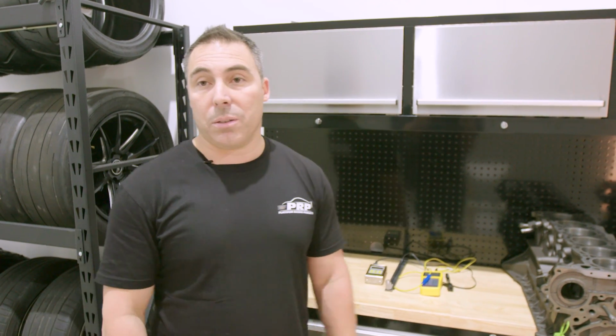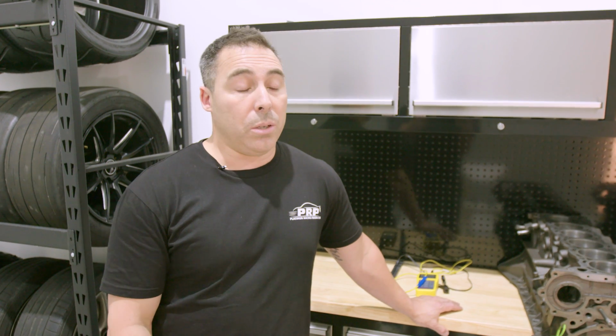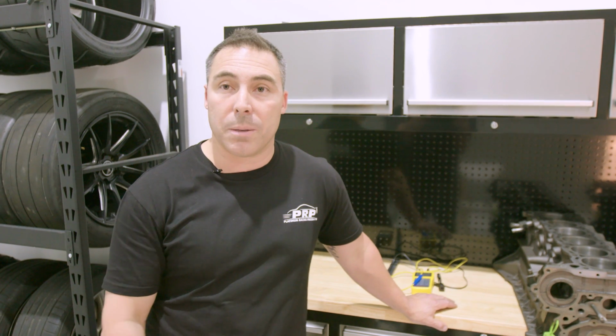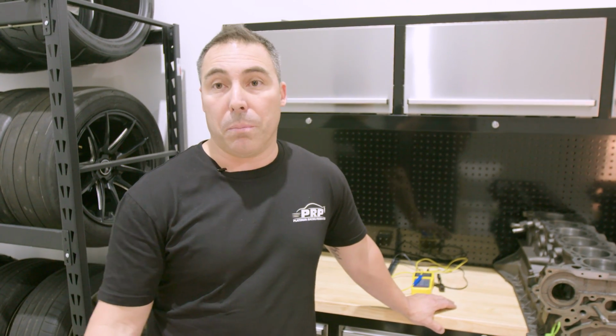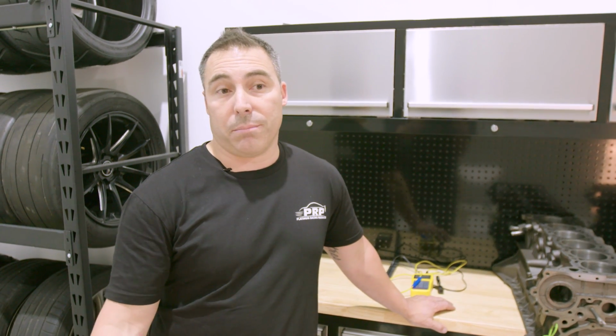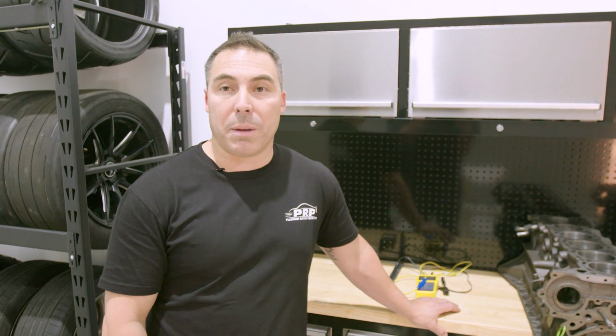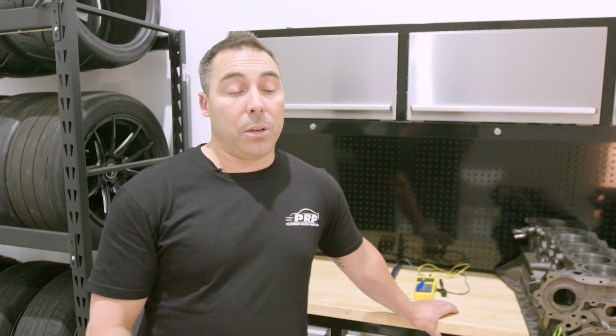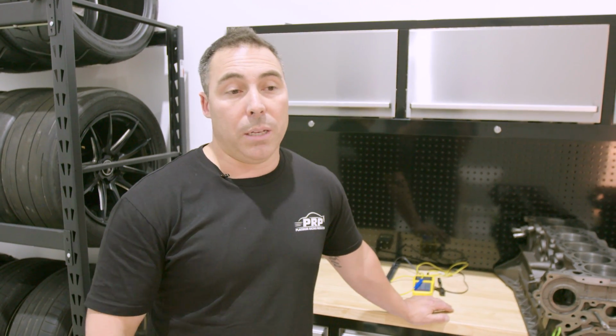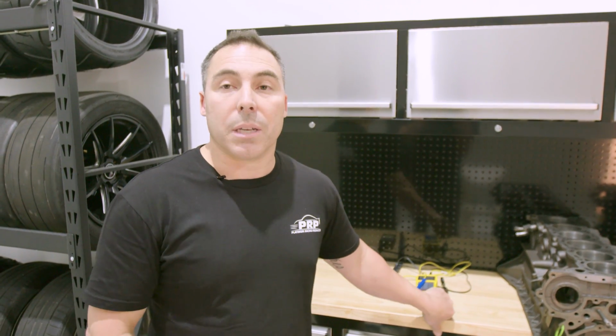All it really comes down to then is bore thickness, because your bore's going to crack whether it likes it or not, if it's too thin. So you want to maintain over about 3mm, which is my benchmark minimum for bore thickness. And you want to stop the bores ballooning, and the only thing that will help is a harder casting. Whether the block was cooled quickly while it was being manufactured will lead to a harder block. If it was left in the cast over the weekend on a Friday, for example, it's going to be a pretty poor quality block. And everything else, as far as I'm concerned, doesn't matter.